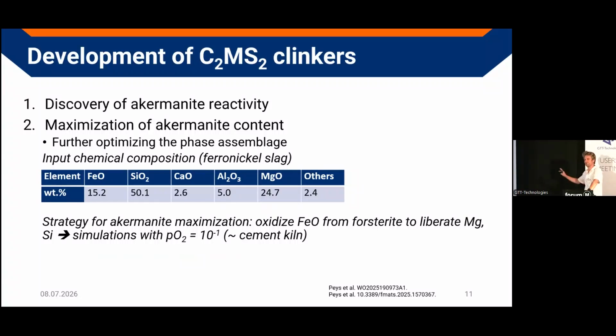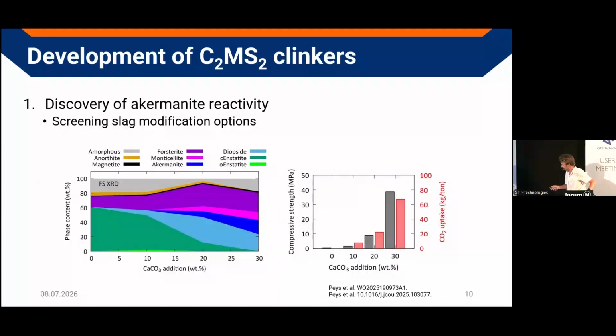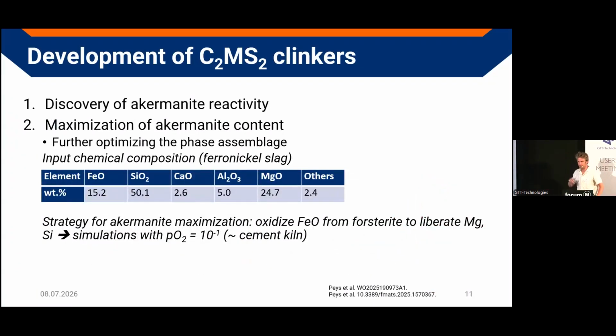We were not completely happy yet, because we still had a lot of phases that are not carbonatable in here. So you see, the akermanite was reactive. Okay, very good. It gave us strength, but it's a bit a waste of energy to make a clinker with only 18% of a reactive component. There's also forsterite here. There's still some diopside, which don't react at all. So then we went to maximize completely the akermanite content.